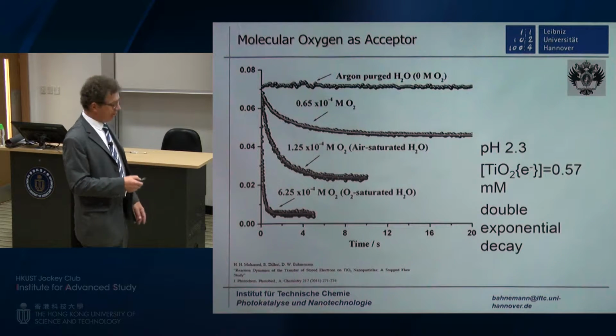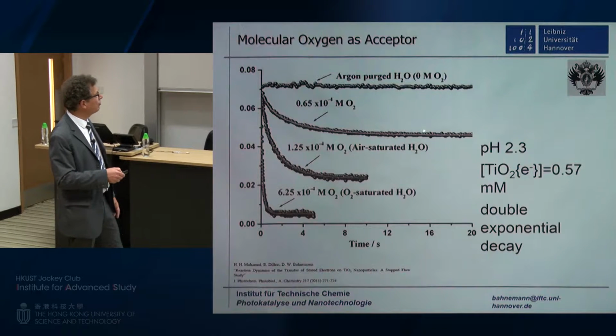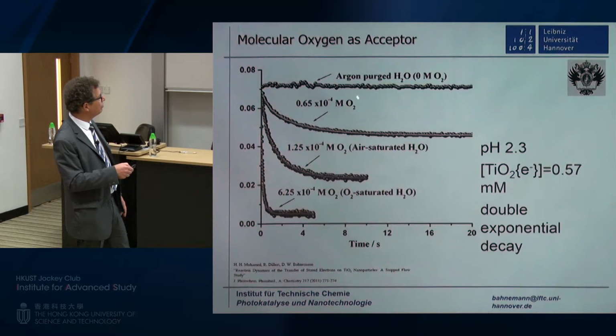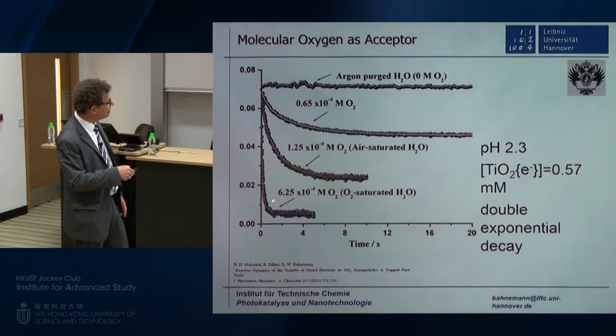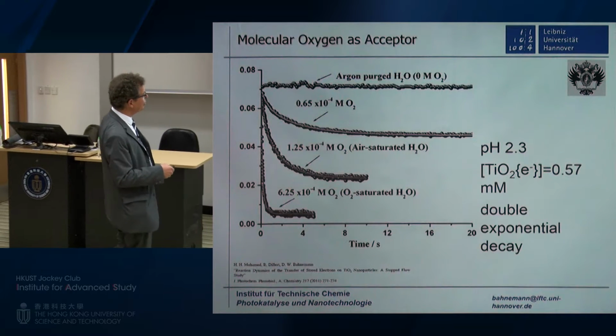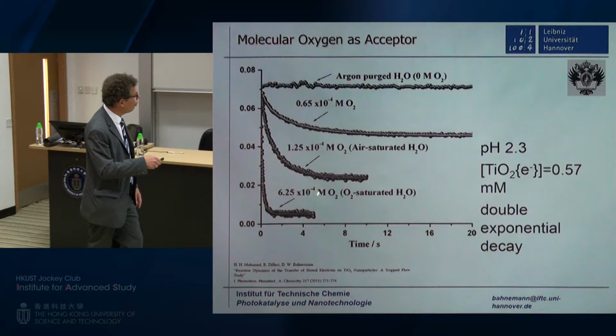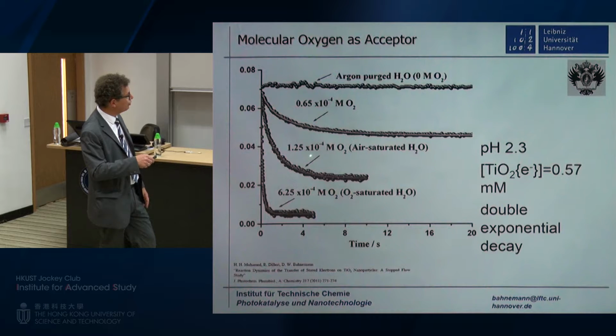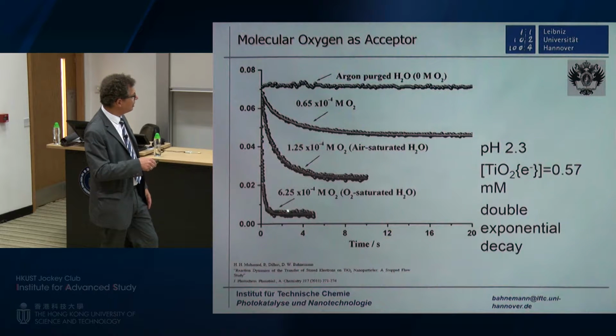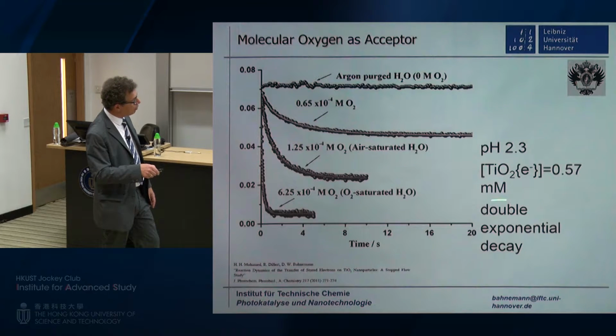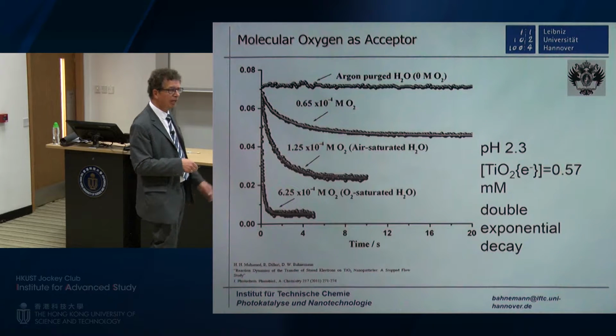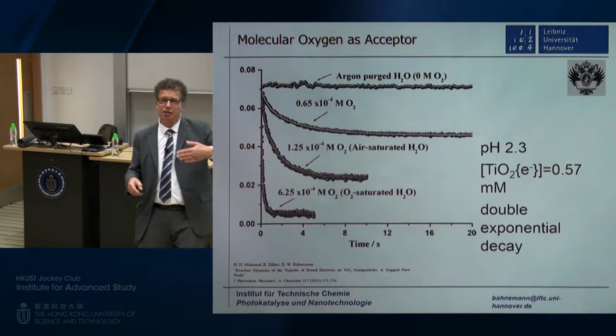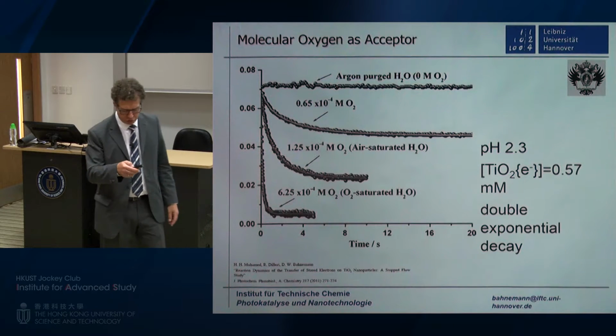You can also see bleaching of the blue color if you, for example, take something like molecular oxygen in different concentrations. As you raise the concentration, you see the speed of the reaction goes up, and you see also that more and more of the electrons are consumed because you put in more, and here about all electrons are consumed. And if you look more closely at the kinetics, you find a double exponential decay. The reaction apparently goes through two steps.